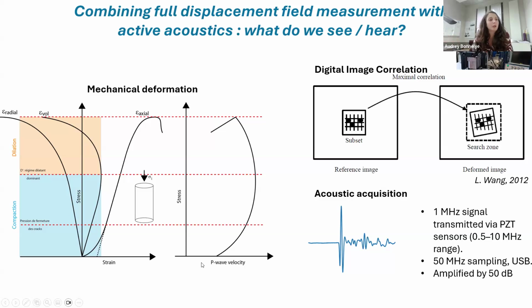And along the experiment, what we can also do is measure the evolution of p-wave velocities. The problem when we do such an experiment is that we are solely considering deformation as a punctual value because we are usually gluing some strain gauges on the sample. But what we know is that deformation is not a single value at a single point. And for this reason, over the past years, some people have been developing techniques based on digital image correlation, which means that we are deforming a sample, and we're following the deformation with a camera,